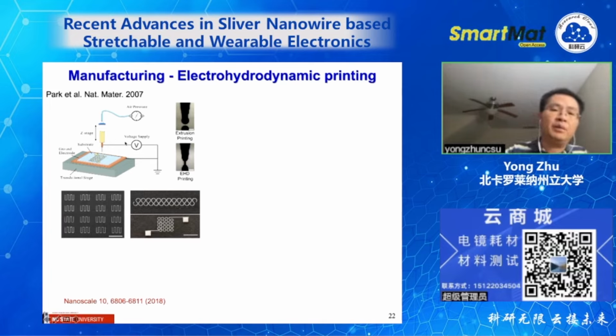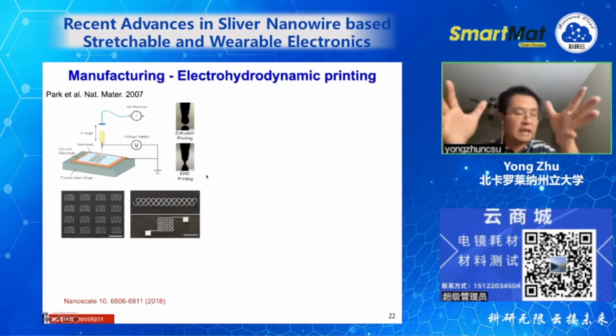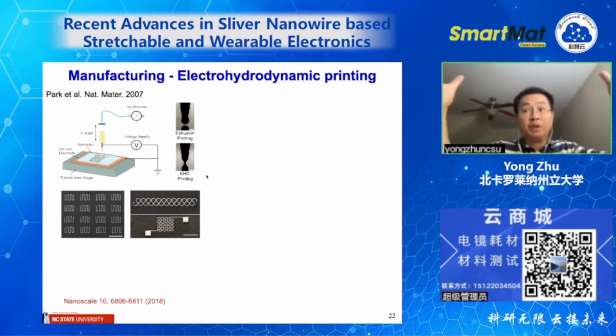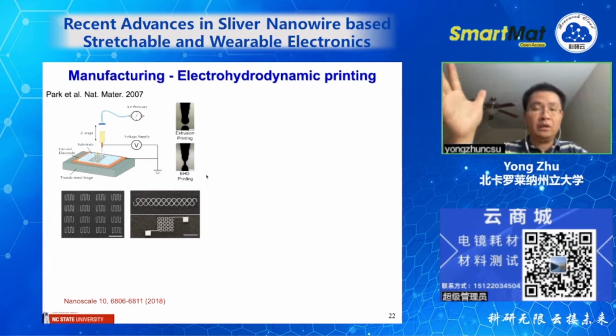Essentially we apply a voltage across the printer head and the substrate. Otherwise, it's very similar to inkjet, but this voltage helps. The mechanism is quite complicated, but in short, it forms something like a Taylor cone. You could have a big nozzle, but the droplet will shrink, and then what you print is actually pretty fine in terms of size. You have a big nozzle to avoid the agglomeration problem, as we said for nanowires, but with this Taylor cone, you can still print fine features.